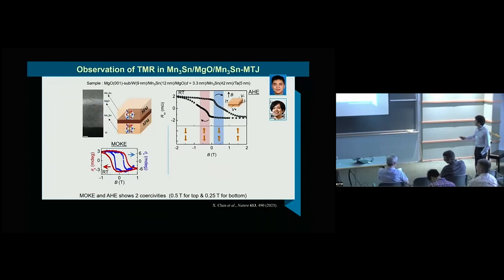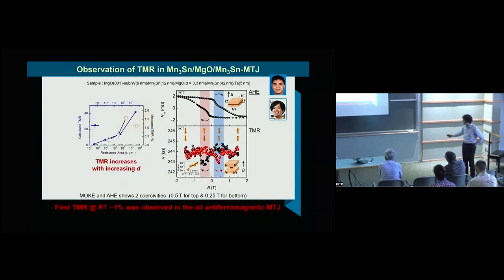Okay, so there is a finite region. The important thing is that this finite region allows us to see the antiparallel octopolar state in this field range. And if there is any change in magnetic resistance, this is coming from the tunneling. And indeed, we see such a change, which, although it's not very large, only about 1%, is actually the first time for an all-antiferromagnetic tunneling junction. And we can make this even bigger by making the MgO thicker.